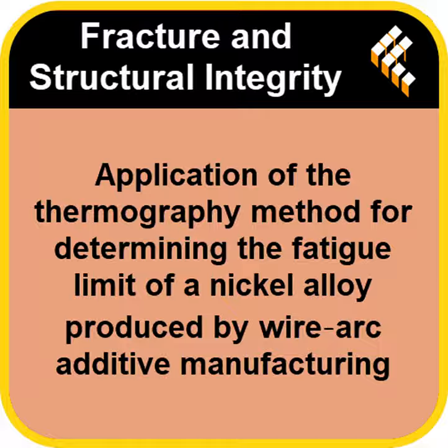Exactly. They didn't just crank up the stress until failure. They ran 11 successive loading blocks. They'd start at a baseline stress, say 300 megapascals. And then in each new block, they'd just nudge the maximum stress up by a small, steady step, about 10 to 20 MPa at a time. And the really clever part is that after each short block, they let the sample cool all the way back down.